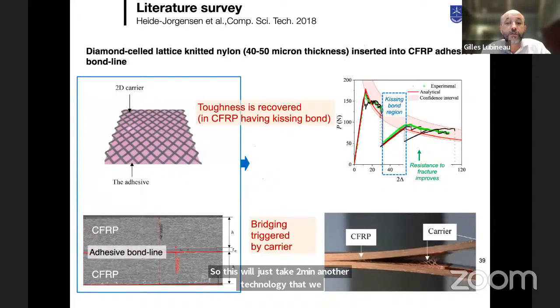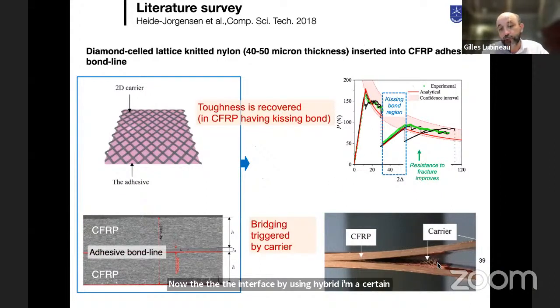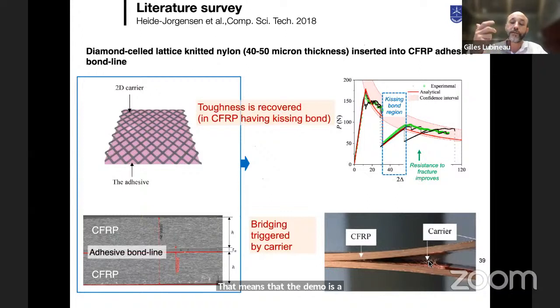Another technology that we are using in the lab is to modify the interface by using hybrid thermoset and thermoplastic. The idea is again to introduce bridging between the top and the bottom substrate, but this bridging is introduced by a thermoplastic net. You know that thermoplastics have much more ductility compared to thermoset. And if you are able to achieve bridging by a thermoplastic net between the top and the bottom substrate, you will also stabilize your joint a lot.